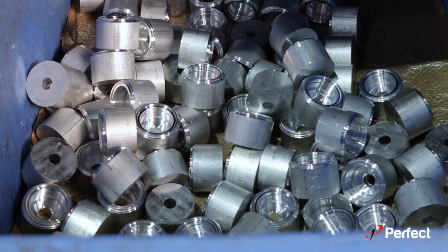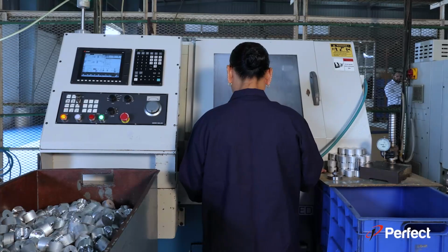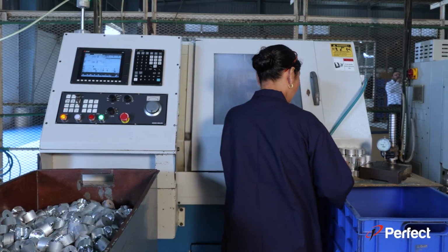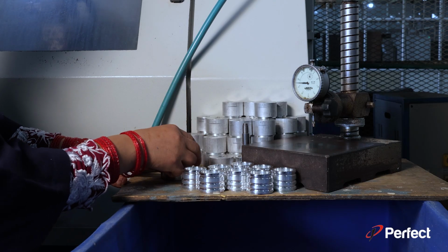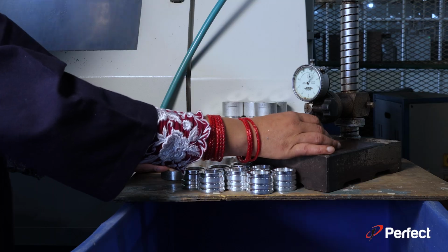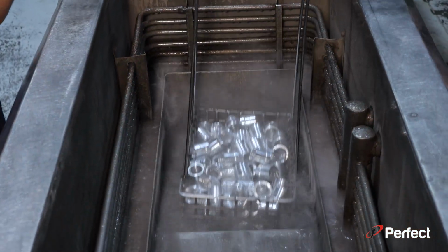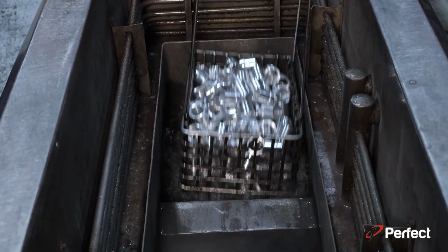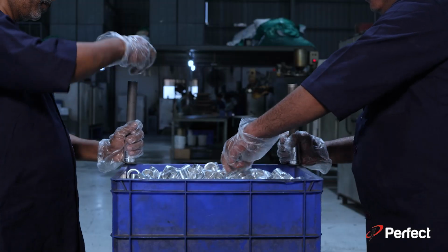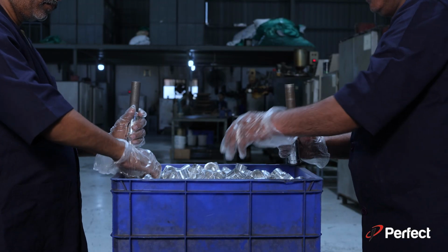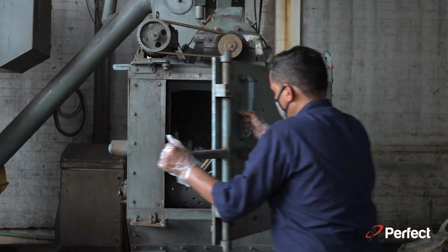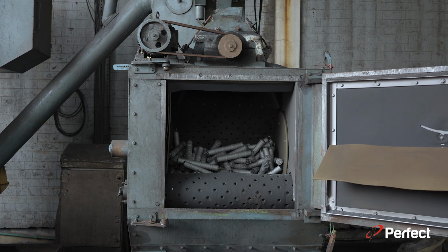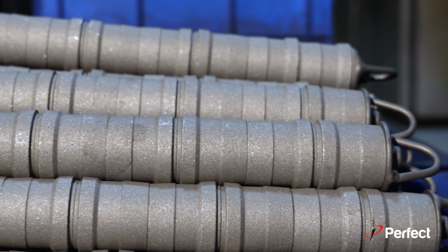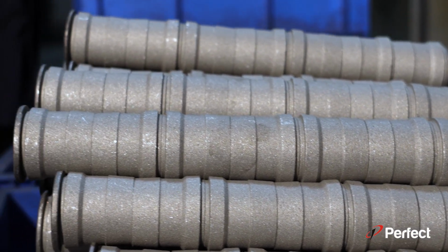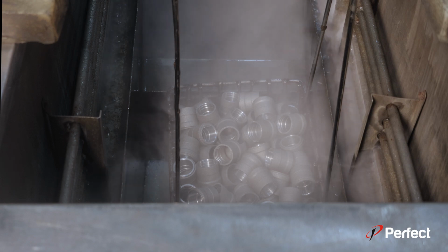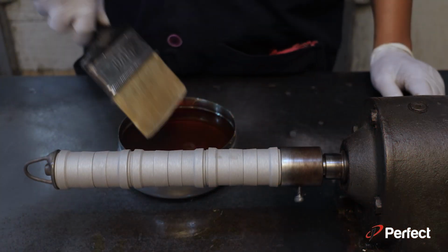Then, these processed inserts are sent for CNC machining to process the outer diameter as per our drawings. These machined inserts are taken to the ultrasonic machine for cleaning with trichloroethylene. The cleaned inserts are then mounted onto mandrels and fixed for shot blasting on the outer surface. The shot blasted inserts are again taken to the ultrasonic machine for cleaning with trichloroethylene.